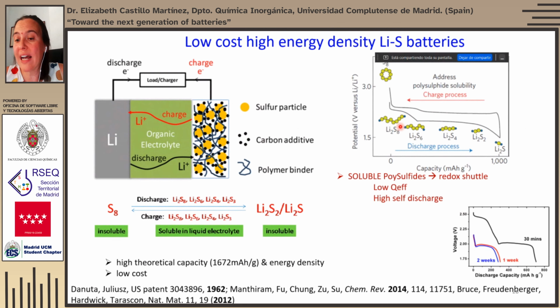And indeed, if you look at how the battery is discharged after 30 minutes of being charged, or after 1 week of being charged, you will see that the capacity delivered gets much lower because these batteries have issues with self-discharge. Of course, there is intense research on lithium sulfur to alleviate these issues, like putting protective layers, making composites, having the sulfur trapped into some carbon nanostructures to avoid these polysulfide redox shuttle events.